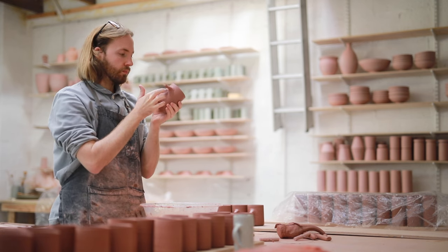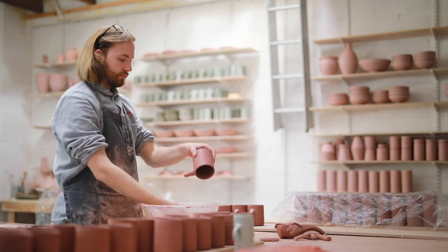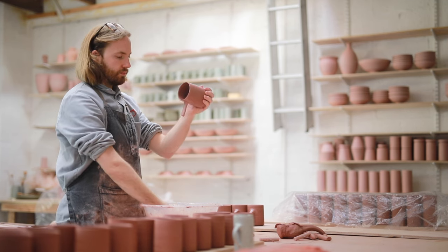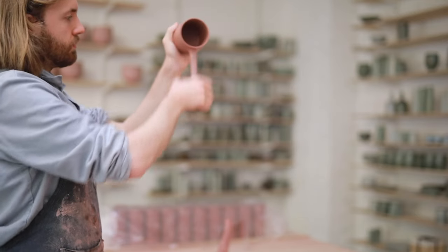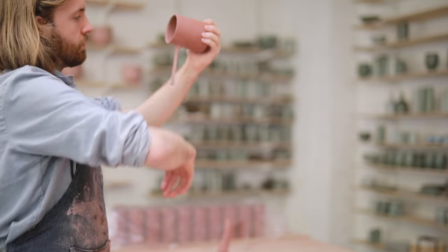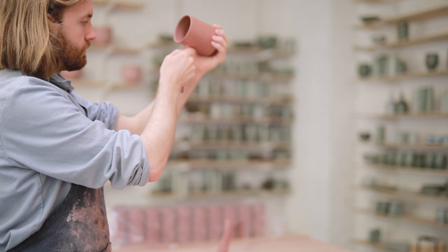Then with a dry finger I blend in the clay from the flare into the body of the mug making it nice and smooth. I then cover the entire handle with water and begin the pulling process again, this time working in a much more delicate way. As I pull, I rotate the position of my hand from side to side, pulling with different orientations and using the crease between my thumb and index finger to act as a kind of template for the wetted clay to run through, which gives it a nice even shape.